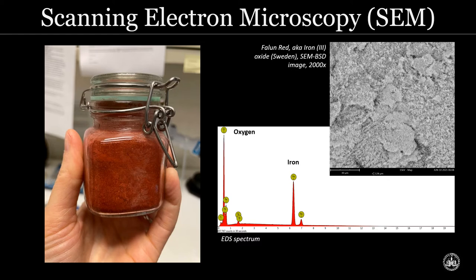So here, for instance, is a sample of some red iron oxide pigment that I got from Falun, Sweden. There it is known as Falun red, collected from an area rich in ochres known as the Copper Mountain. And in the spectrum here, you see major peaks for iron and oxygen from those iron oxide minerals. And often when I analyze naturally sourced ochres, I see a lot of other elements like calcium, silicon, and aluminum from the other minerals that are associated with that source.